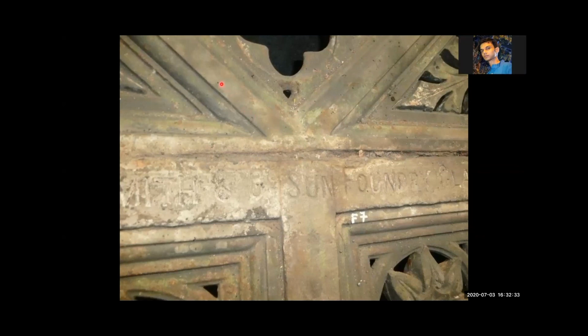And it's where the little bubbles, maybe of air that came in with the metal, or maybe it's steam generated from the sand mold, rise to the top of the mold, and that means that on the top surface of the casting, you get these tiny, tiny bubbles which just break the surface. Now, whereabouts is your dip material going to go? It's going to get drawn into these little tiny holes and into any other small areas.